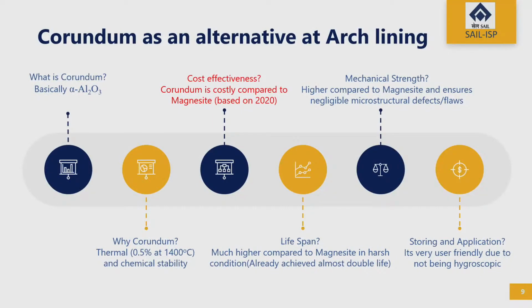So initially, as I mentioned, we used magnesite as an arch material. Right now we have switched to corundum. Corundum is nothing but alpha alumina, with thermal expansion of plus 0.5% at 1400 degrees centigrade, and has better chemical stability. But here I marked it red, that cost effectiveness is not there, because corundum is much costlier. Based on our ISCO data, one set of magnesite arch costs around 32 lakhs, whereas corundum costs us almost around 45 lakhs.